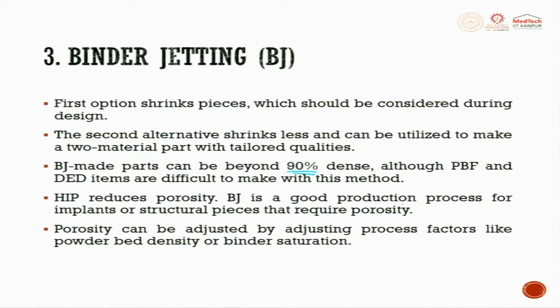Binder jet is a good production process for implants or structural pieces that require porosity. So, wherever you intentionally need it, we also try to induce this by binder jet porosity. Porosity can be used for advantage as well as for disadvantage. So, you tune the pores for your benefit. Porosity can be adjusted by adjusting process factors like powder bed density or binder saturation.